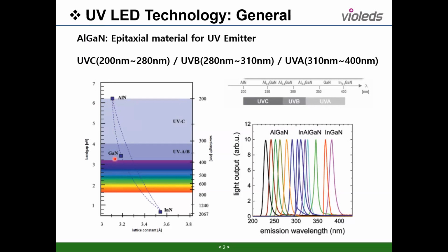Actually, if there is a pure gallium nitride layer, then the light is close to the UVA wavelengths, and to the wavelengths of the blue. You know that to make white, usually we use the blue LED together with the yellow phosphor. In case the emission layer in the LED is indium gallium nitride, there is some indium content there to go to longer wavelengths. So you see that the composition of aluminum, gallium and indium is very important.